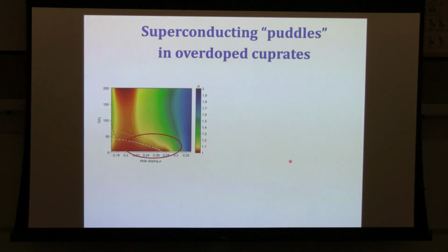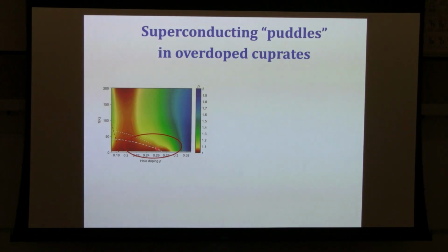Okay, so how do we understand this sort of behavior? We have strange metal behavior that seems to be tied somehow to unconventional superconductivity. The two seem to terminate at the same point. They're correlated, and also they're quantitatively correlated. Where Tc is high, the coefficient of the linear in T scattering is also large. So if you like, there are two logical ways to approach this.